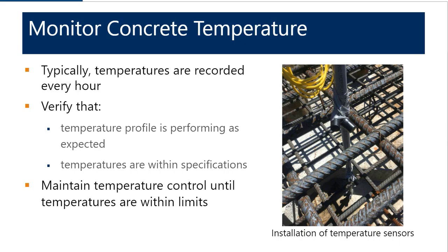And so on the right-hand side, you can see a photograph of temperature sensors that were installed into a mat foundation. In this particular case, the temperature sensors, the wires were threaded through a piece of conduit that was spun up to the top. And so it's just an easy way to keep the wires pseudo-protected during the placement operations. One of the things to keep in mind is to secure those sensors such that they don't press up against the reinforcement. So you're actually measuring the temperature of the concrete and not the temperature of the reinforcement.